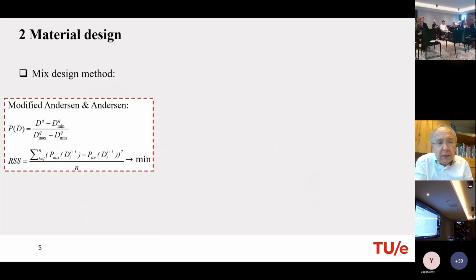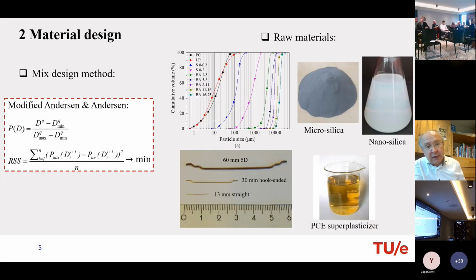Well, when you use all these different size classes, you need to proportion them in the right way. And we have our own mix design software that we also use for, let's say, normal concrete, but also for this concrete, where we apply many different sizes, not only fines, cement and filler and nanosilica and so on, but also coarse aggregates. You need to do a good particle design. Mix design. So here you can see some particles that we use, including the particle size distributions. This is micrometer. Here you can see 10,000 micrometer. That's 10 millimeter. Well, we go beyond, you can see here. And here we have the fine particles that are in the range of 1 micrometer to 100 micrometer, typical cement range, for instance. And all these particles, this is a logarithmic scale.